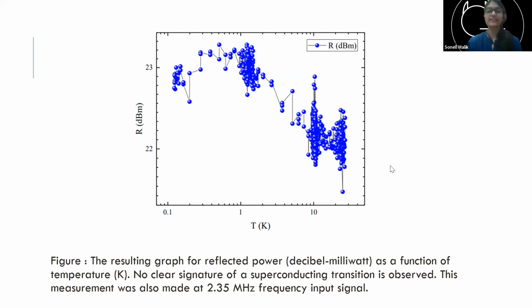So yes, we did not observe a clear signature of superconductivity for the titanium palladium thin film. And also magnetic coupling is a much weaker phenomenon to depend on. The reason I decided to go with the microstrip method and not have direct contact with the thin film was because we were putting the sample in a dilution refrigerator. Now, to make contacts on a thin film itself, earlier we used a quartz crystal, and there are clips that you can connect on the quartz crystal. Now, if you have a sample that has been made on a silicon chip, you can't use clips like that. You will have to use surface contacts. And these contacts are very hard to make. They're made of very thin gold wires and indium solder, and you need to press it on, and they also come apart very easily.